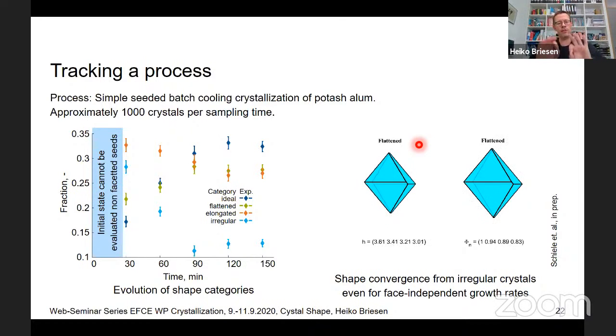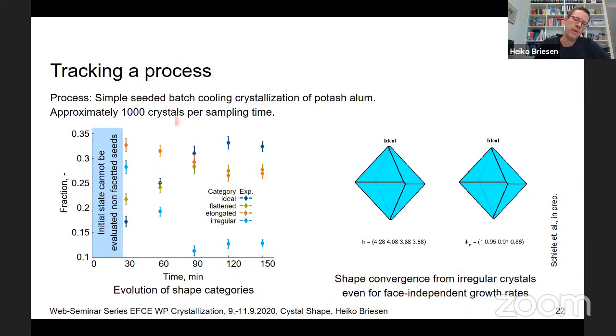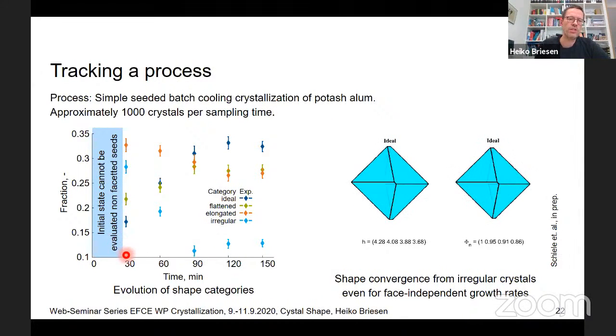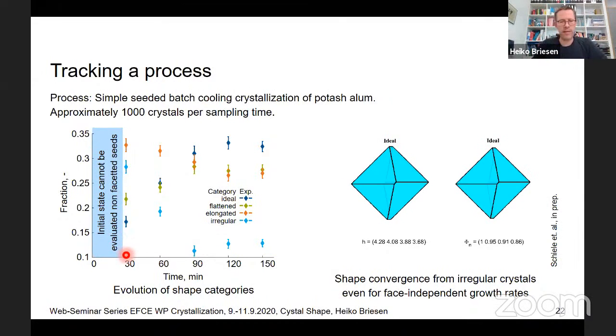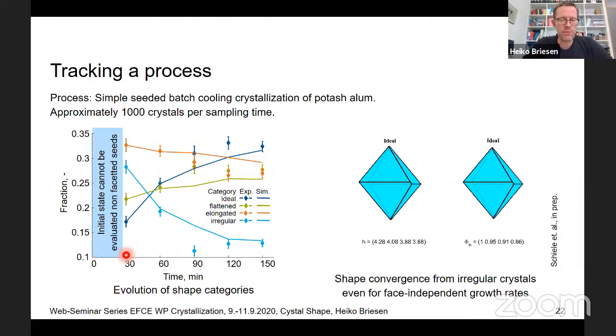If you consider this as the major mechanism, you can start with doing a simulation, starting with this as the initial condition, and let it run with face-independent growth rates, and you would end up with something like this, which is not too bad. I mean, we do not perfectly hit the values you see here, but the tendency pretty much looks like this should be the governing mechanism here.